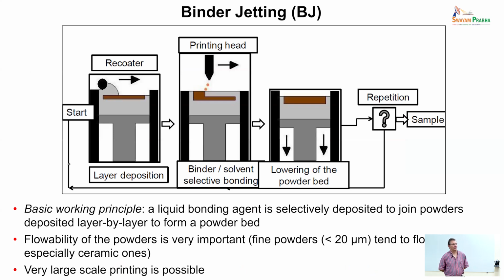Another technology that has been used quite a lot for ceramic feedstocks is binder jetting. Binder jetting has this specific working principle. You have a way of depositing your powder layer by layer. And after you deposit a layer of powder, you have a printing head that deposits a bonding agent. And the bonding agent binds selectively the powders that you have just deposited. And once you finish inscribing that layer, the part lowers, and then you coat again the part. You generate a new layer of fresh powder, and you repeat the process, giving a different shape.